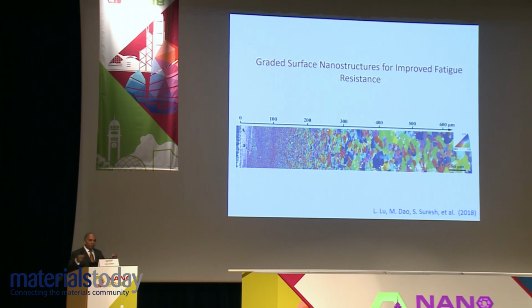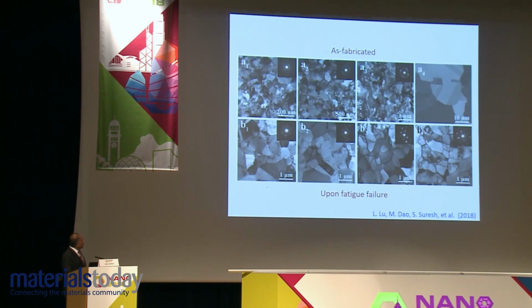And then we mechanically fatigue it in cyclic loading at room temperature. As we mechanically fatigue this, we find that over a course of time, just as it happens in any microcrystalline material, there is a continuous change in microstructure. In traditional materials, you form dislocation networks, dislocation dipoles, veins, persistent slip bands, which cause intrusions and extrusions, etc. In the case of copper, which is surface graded, you have an opportunity to change this dramatically. So let's see what happens.